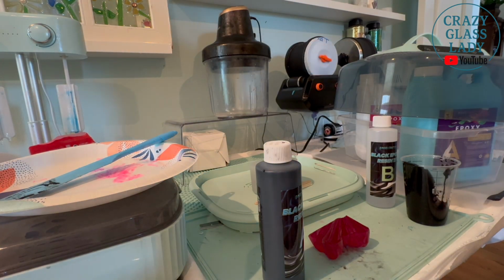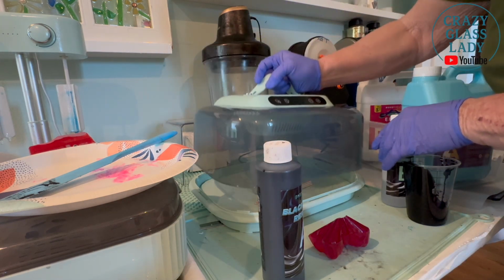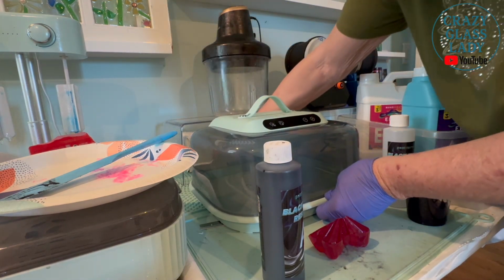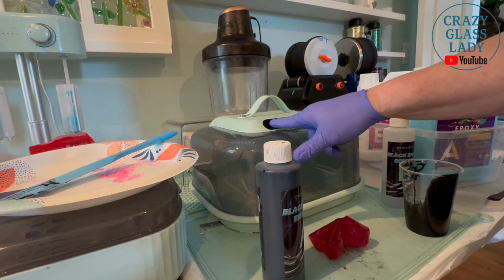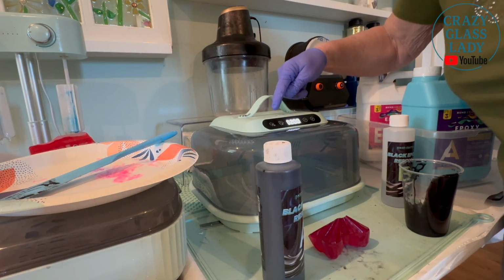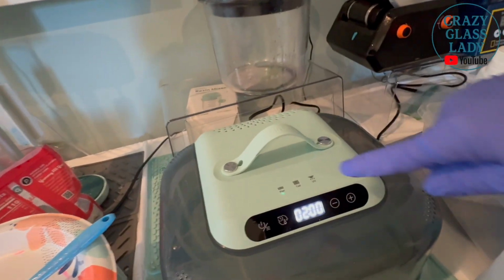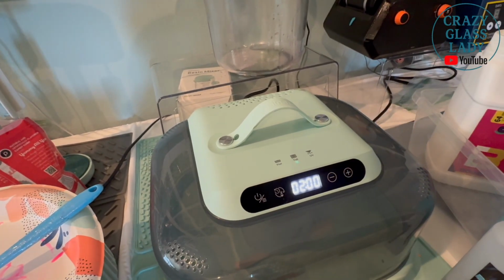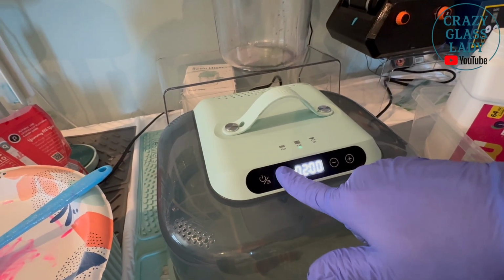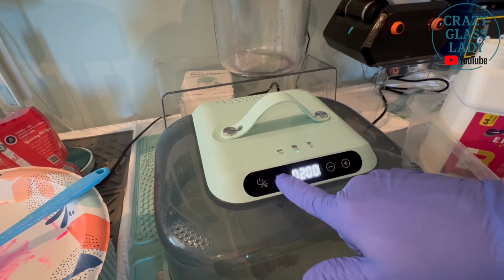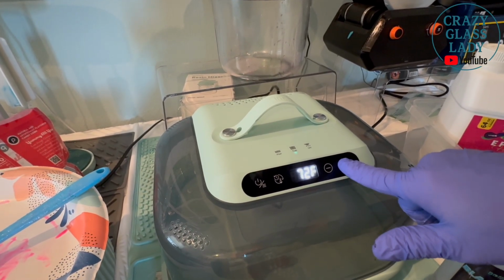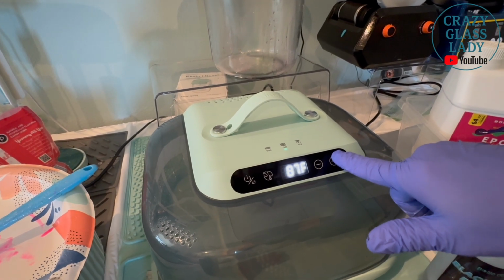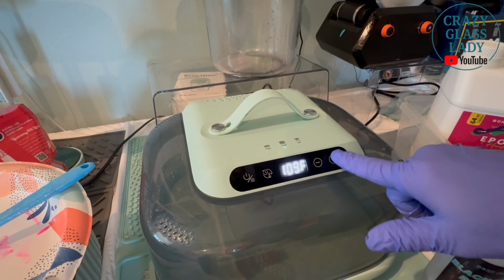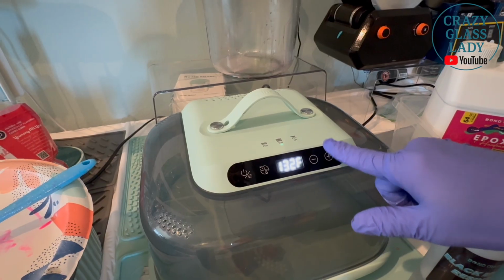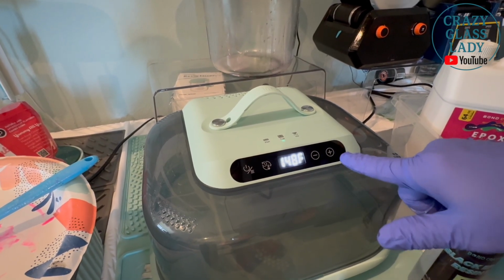And here I'm using the Resiner's new G3 2-in-1 curing machine. It can actually cure the 1-to-1 resin, the regular epoxy resin, and also UV resin. So it's really neat, and I'm going to have a video out later this week about it. You just turn it on by pushing that button, and like I said, I'm going to do a whole video on it, but you can select the short mode, the tall mode, or the UV mode, and you can also choose how long you want it on, if you're doing the regular epoxy resin, for how many hours or minutes, and then also select the temperature that you want. So my bow will be ready in 2 hours, and then I let it sit for half an hour to cool. So it's really like using a fast cure resin.